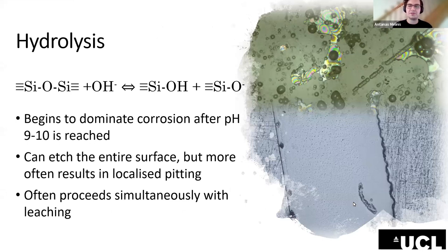The other phase is the mode of hydrolysis, which steps in when the pH is strongly alkaline, which is not so common in natural environments, for example, soils. So here the silica network itself is attacked and gradually dissolved. And you can see these pits, which are most frequently caused by the alkali that I previously mentioned, that accumulate in small clumps on the surface and just sort of grind through that surface because of the highly alkaline solution that they create with water from the atmosphere or the soil. And both of these processes can happen simultaneously with one or the other dominating on either side of the pH scale. And of course, by no means exclusive, and there are many others, but in the interest of brevity, this is the general understanding of glass corrosion.